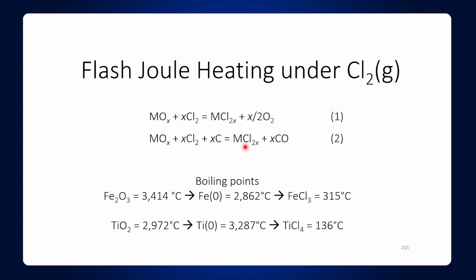Well, why would we want to make the metal chloride? Look at this. Iron oxide boils at 3,400 degrees, and iron metal at 2,800. Again, still very high. But iron chloride is at 315, so a much more accessible temperature. Titanium oxide, almost 3,000. Titanium metal, which is titanium zero, is 3,200, 3,300 degrees. Titanium tetrachloride, 136. So you see how much easier it would be to distill these away.